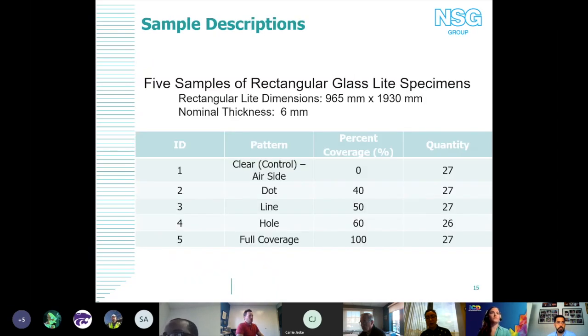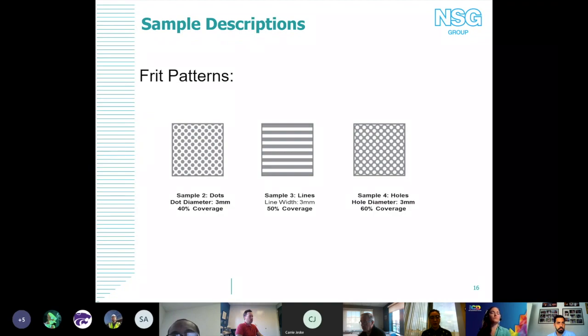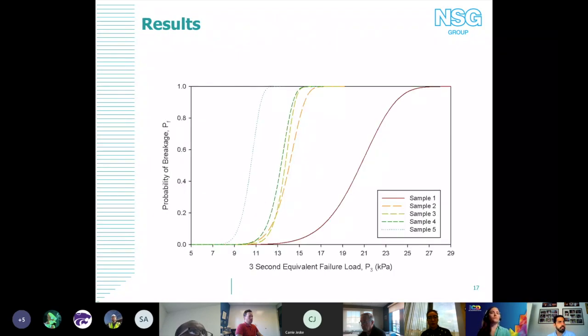What we did was we tested our control, and then we had varying percent coverages with this frit, and it was all a gray frit. So we did 40, 50, 60% coverage, and then a full coverage. Move forward, and you can see an example of what the patterns look like. We had our dots, our lines, and essentially the reverse of the dots, so we just had these holes. Again, here you see the distribution of them.